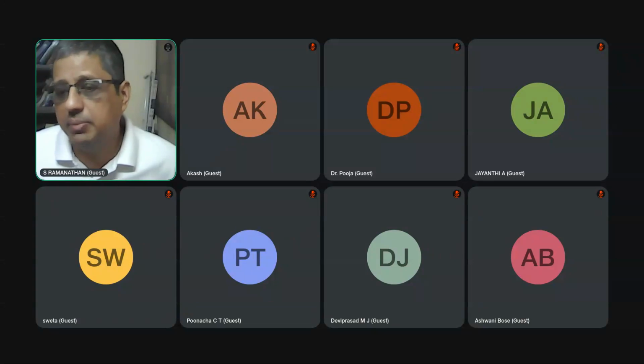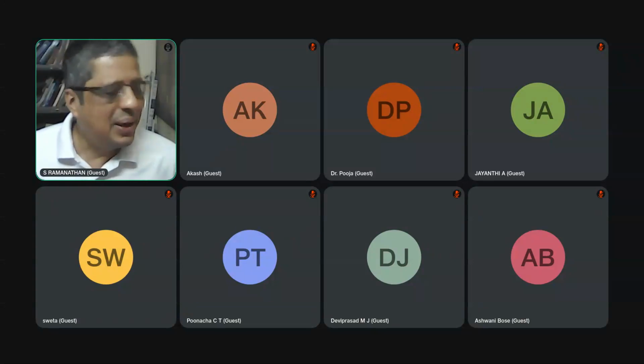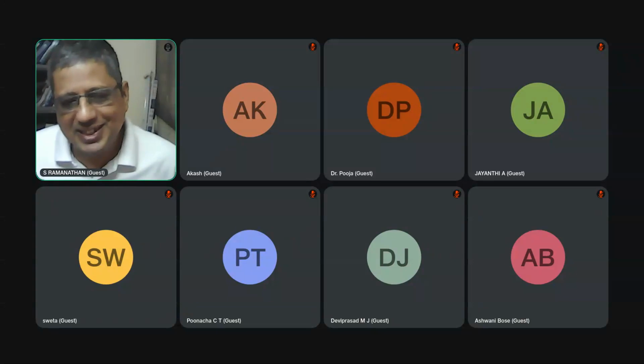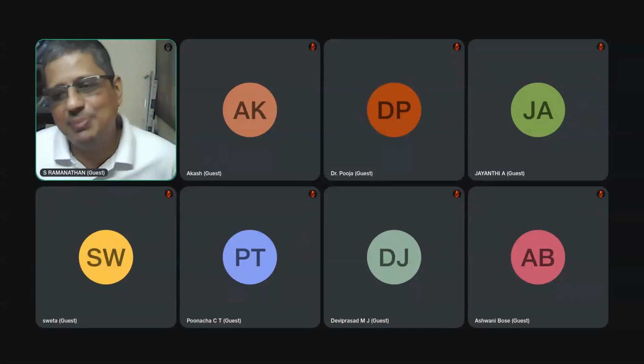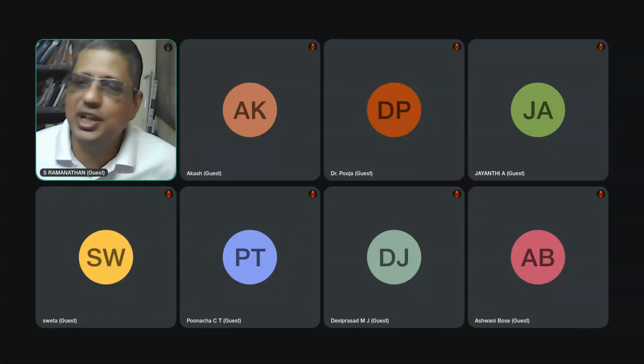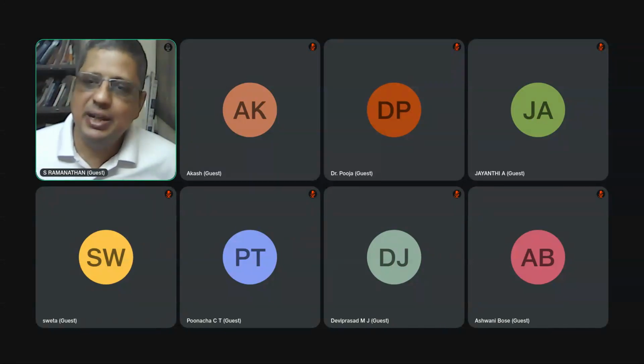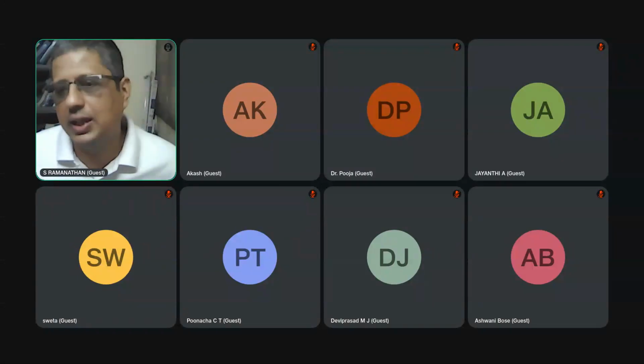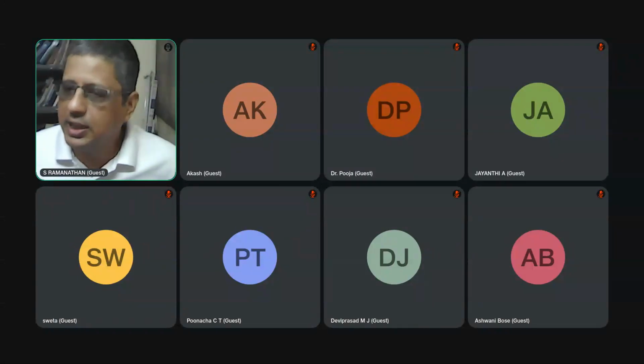Static condition, how to include dynamic conditions of the electrolyte. So if you want to measure the corrosion rate when the electrolyte is flowing, you have to do the experiment also when the electrolyte is flowing. Then you can do that. Okay. So corrosion cells typically have static electrolyte, but doesn't mean you have to conduct the experiment in that way. You can conduct experiments in rotating disk electrode. You can conduct in other flow cells. It is fine.